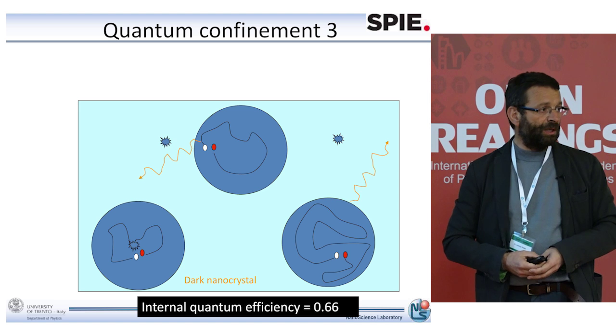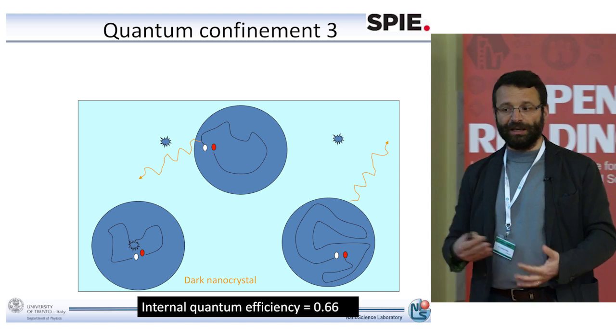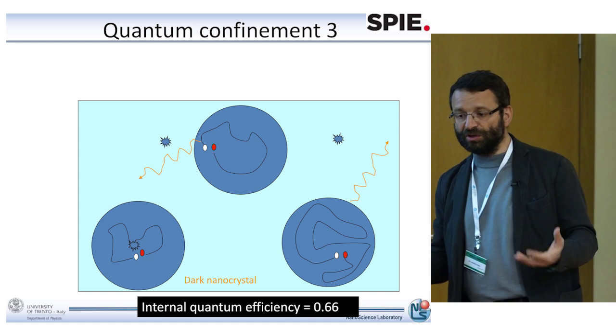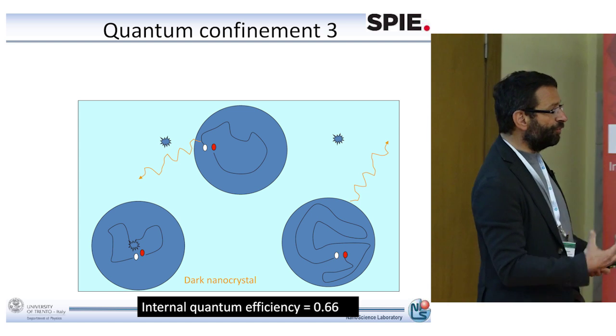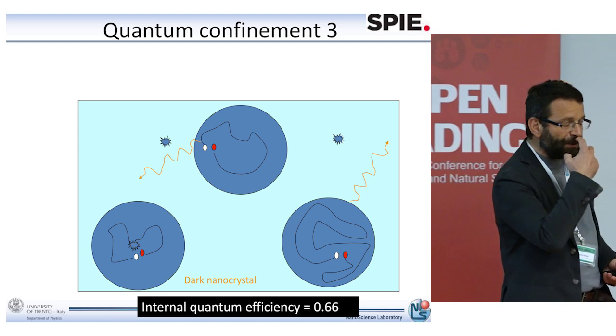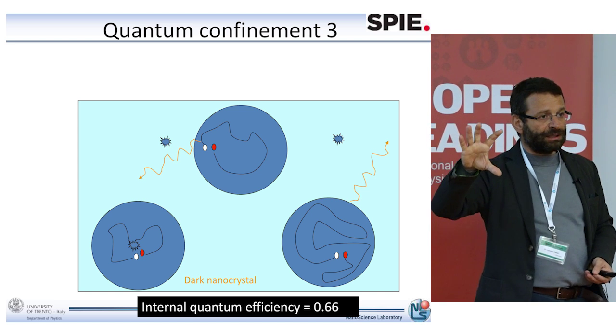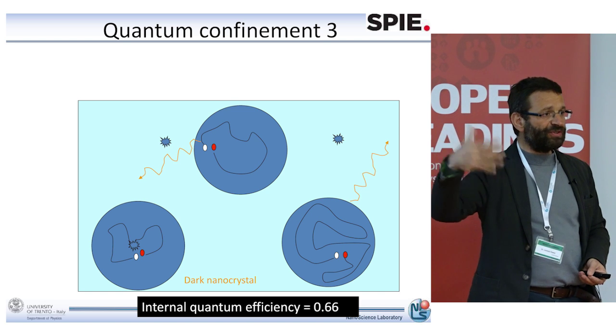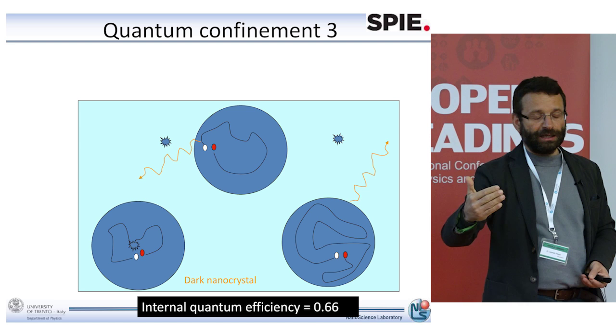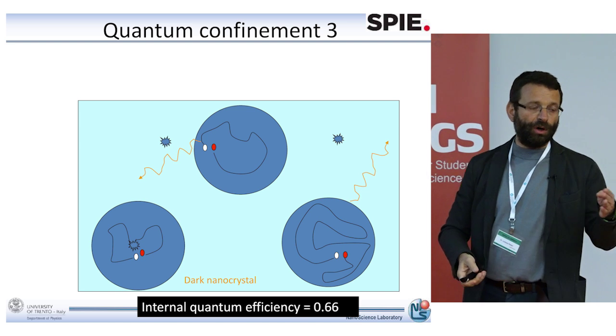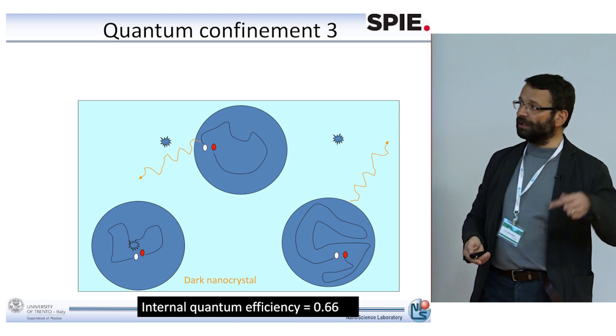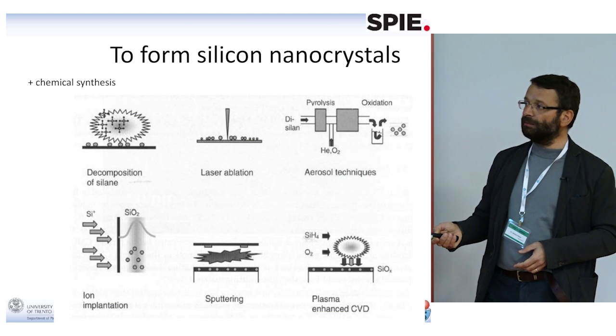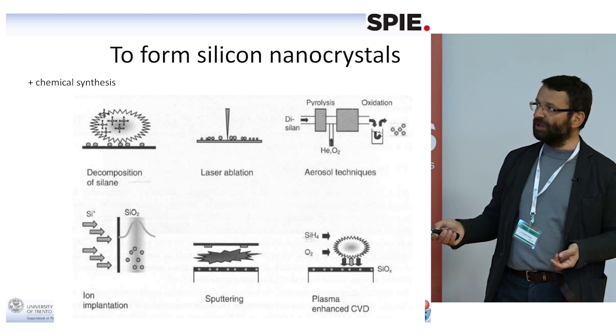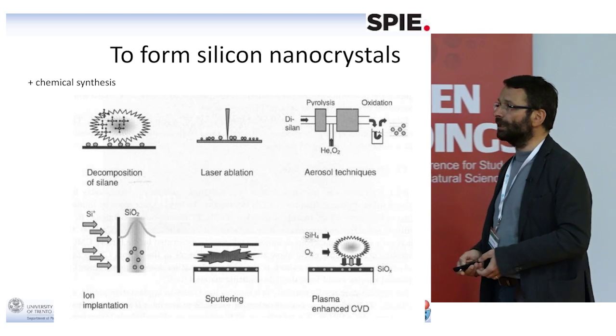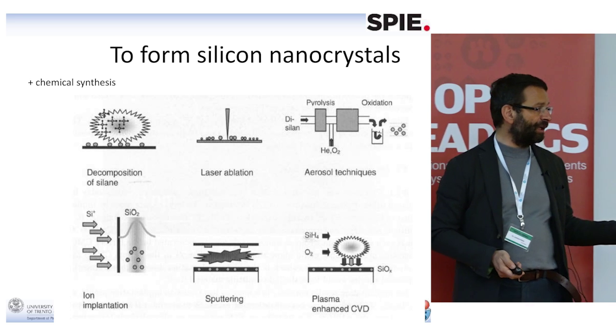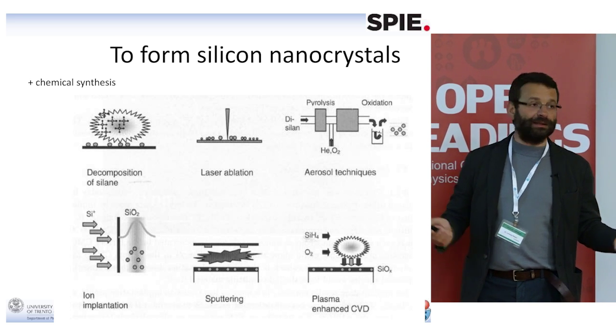Very easy, very simple. What you typically have to do is, by any means, form a substoichiometric silicon oxide. So you have to deposit, implant, whatever you want to do. You have to make a glass, a silicon oxide, with excess silicon, with some more silicon. So you form a substoichiometric silicon oxide, or silicon-rich silicon oxide. And you can use ion implantation, sputtering, chemical vapor deposition, or more exotic techniques. Once you form this silicon-rich oxide, you simply anneal the film.